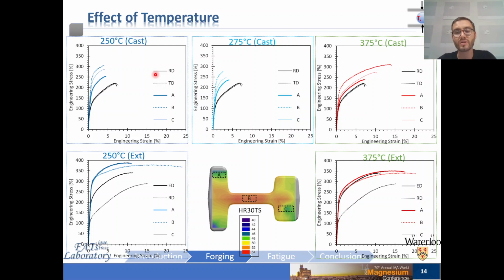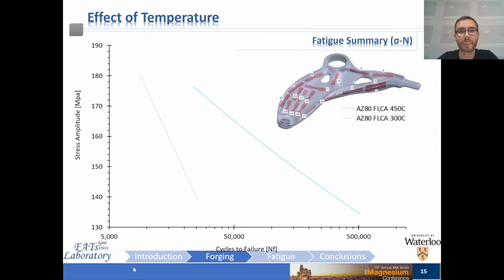Linking that back to a previous observation, the superficial hardness correlates well with the yield strength of the material in various locations throughout the cross section of the forging. So you can see locations A, B, and C here shown in each of these plots. The other important observation is how the base material is modified due to forging. There's a much more pronounced improvement due to forging when the starting material is cast, whereas the improvement when you start with wrought material as the base material is somewhat more marginal, as one might expect, since the base material in the wrought form already has a lot of the beneficial effects of having a wrought microstructure.